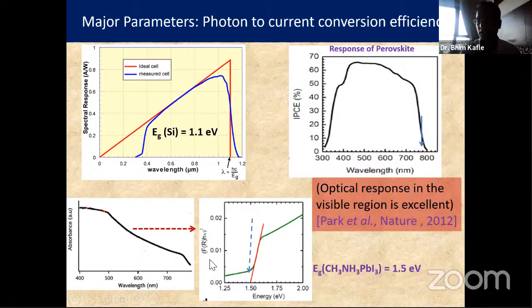the efficiency. Photons impinge on the surface of the perovskite, and how many photons are converted to electrons can be represented in this curve as a function of wavelength. You see here, the current conversion efficiency very much reflects the absorption curve, let's say up to 780 nanometers. There is very good correlation, and we can see that about 60% of the solar radiation can be converted into electricity by this kind of material.